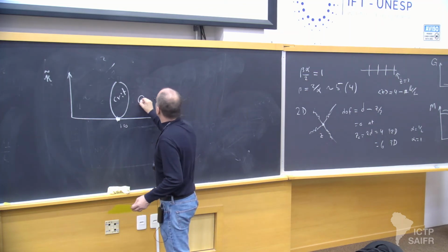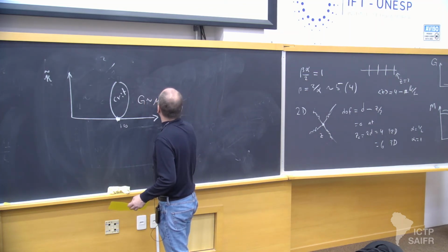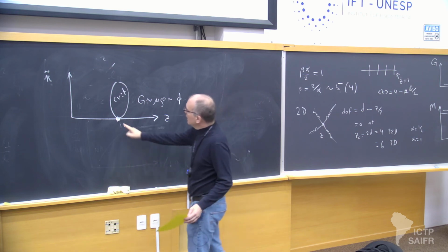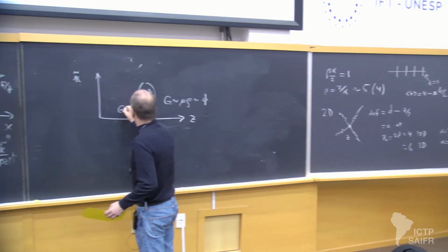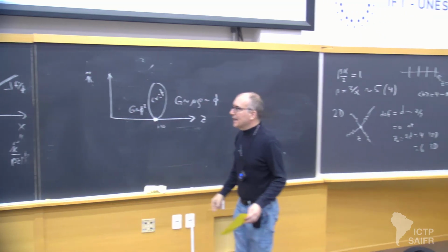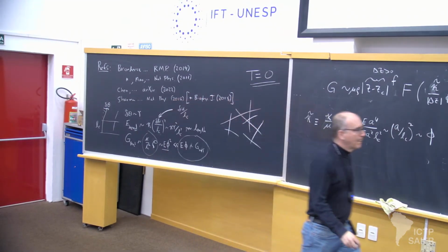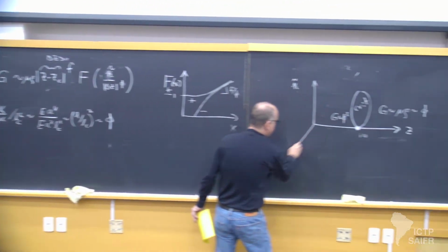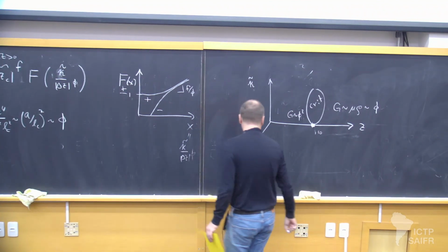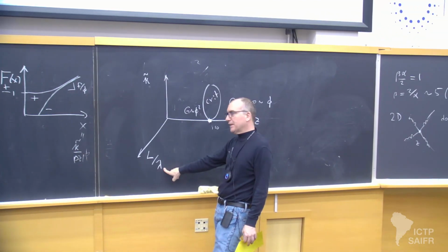Over here, the modulus is proportional to mu rho, i.e. 1 power of volume fraction. Down here, G goes like phi squared. It's that low modulus of this picture until I extend the fiber length. So as I indicated, there's this non-affine length lambda.